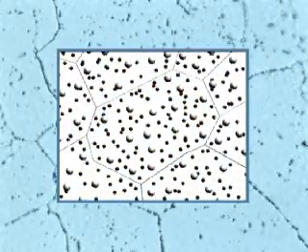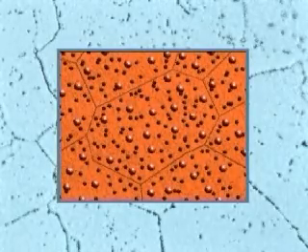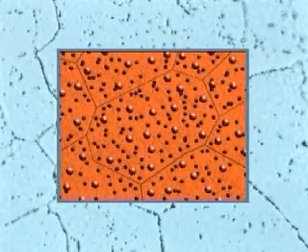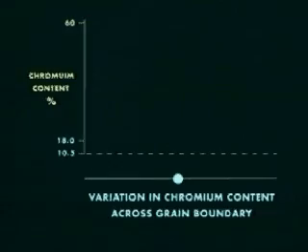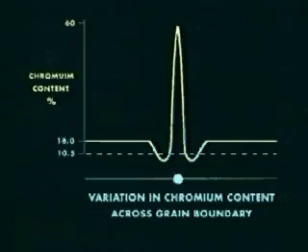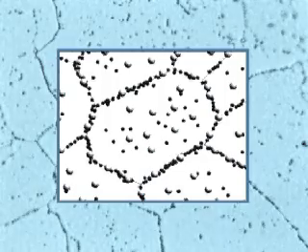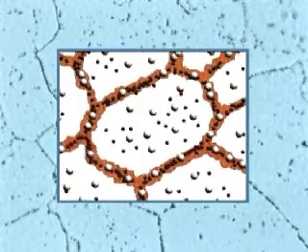As you may expect, a piece of stainless steel normally has the same chemical composition at any location. However, if it is heated to between 500 and 800 degrees Celsius, particles of chromium carbide could start to form at grain boundaries inside the steel. If this happens, the chromium content decreases at locations near the carbide particles. The total chromium content hasn't changed, but the chromium atoms are no longer evenly distributed. There is insufficient chromium at locations near the carbide to produce a passive film, and corrosion occurs along the grain boundaries.